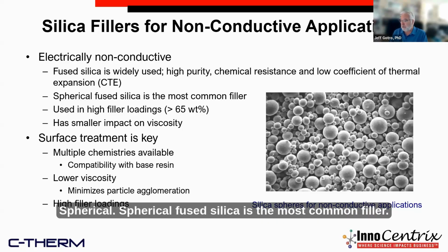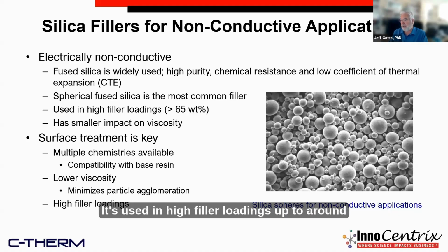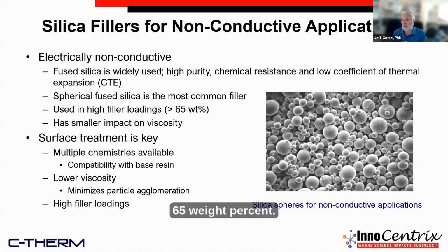Spherical fused silica is the most common filler. It's used in high filler loadings up to around 65 weight percent. And because of what we talked about before, the spherical geometry has a smaller impact on the viscosity.